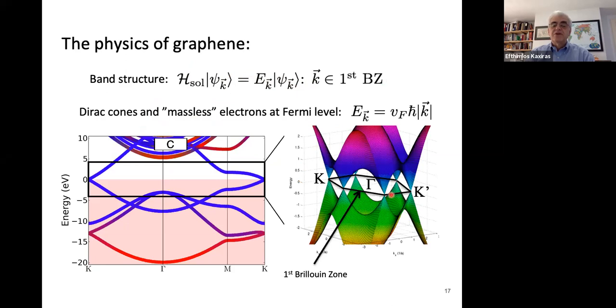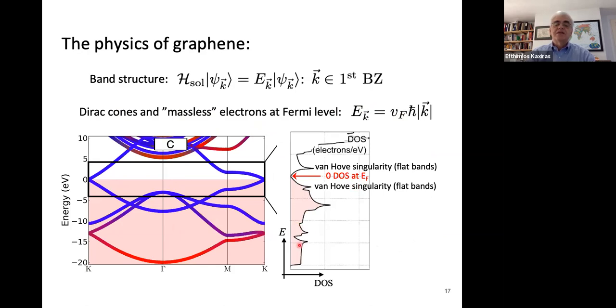Here's the Brillouin zone again in perspective, and this is the energy in the kx and ky components of the wave vector. This is a small region of the energy versus k vector diagram, around the Fermi level. The shaded is occupied levels, the empty is unoccupied levels, and you see these characteristic bands of graphene, which near the Fermi level have this behavior of the Dirac cones, where the energy is proportional to the magnitude of the momentum. This is quite unusual for solids, so these are referred to as massless electrons at the Fermi level.